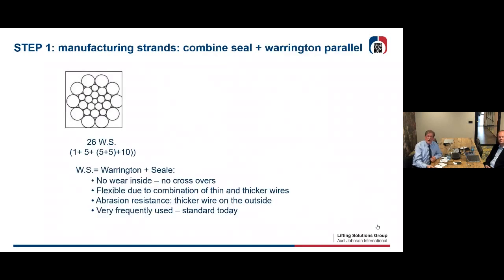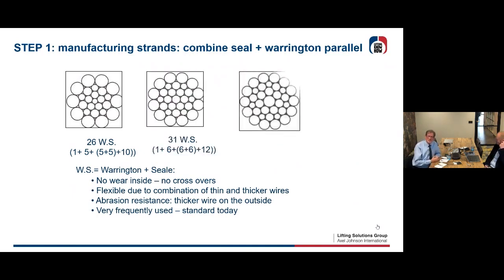Then there was another very good idea to put the Warrington and the Seale construction into one construction, and that's what we call the WS, Warrington Seale. It's a combination: in the second layer you have alternating thin and thicker wires, and then you seal it up with the thicker wires from the Seale construction at the outside. These are very common and used many times in steel wire ropes. You're going to end up with 31 Warrington Seale if you start with 1 + 6, then 6 thick and thinner wires in the Warrington layer, sealed up with 12. You count it, it's 31 Warrington Seale.